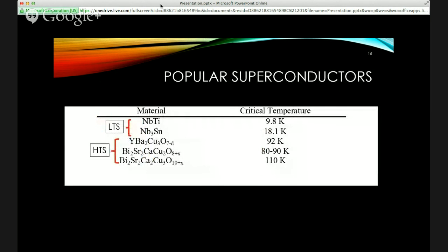So some of the more popular ones, and I'm actually missing one from here, which is MgB2, or magnesium diboride, which sits in its own plane. Some people categorize it differently. But for LTS, niobium tin and niobium titanium. And for HTS, yttrium barium copper oxide, or YBCO for short, or bismuth strontium calcium copper oxide. You have two different chemical compounds. One is BSCCO for short, and then one is B2212, which is that first one with the 80 to 90 K critical temperature. And then you have B2223, which is the 110 K critical temperature.